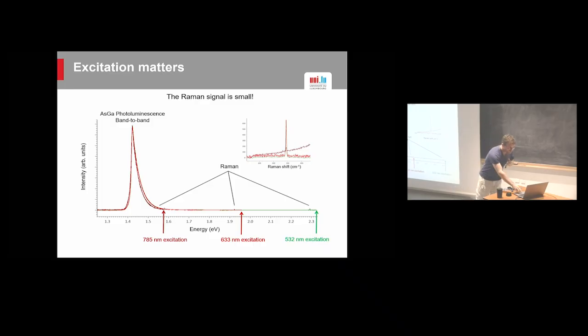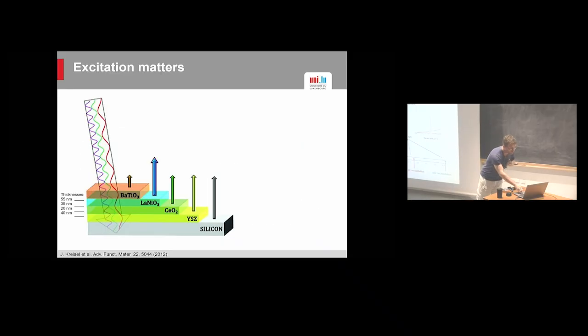There is this other very nice example as well that was published some time ago by Jens. It's a particular system, but it's a nice example of why you want to choose your wavelength carefully. So here what we're talking about is this sort of structure. The topic was integration of barium titanate and silicon and so on. So we have a stack with silicon, yttria, cerium oxide, lanthanum nickelate as an electrode, and barium titanate. Okay, so this is what you have. And what they did in this experiment is that they did it with different wavelengths. Okay? And what you see very much depends on the wavelength that you're using.